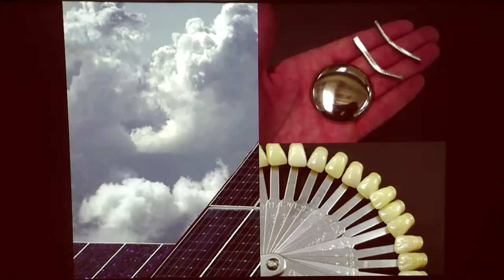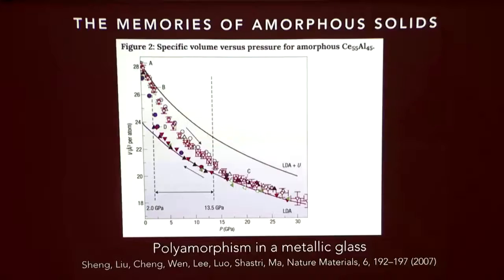But under the right conditions, with the right alloy, quenched at the right speed, you can create a metallic glass which looks just like any other metal, but has some very interesting properties which make it potentially of industrial application. Those are that it is high strength. Since it doesn't have any dislocation defects built into the structure, it gets to much higher stress before it starts to exhibit plastic deformation. In addition, because they don't have any grain structure that develops, they're easy to form through near net shape forming. Basically you can heat them up to near the glass transition temperature, they become highly viscous, and you can push them into a mold, and you don't have the problem of shrinkage associated with the first order phase transition, or the grain structure interacting with the mold. So they're potentially industrially interesting materials, but they have some bad failure characteristics that we'll talk about.